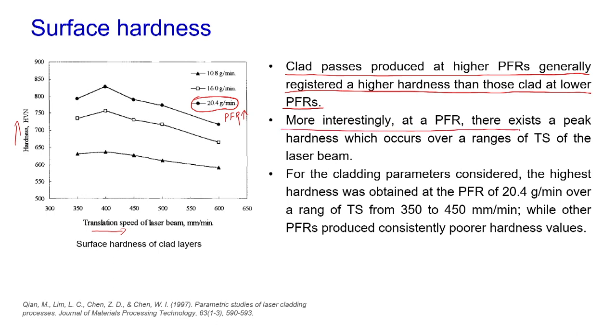Interestingly, at a PFR, there exists a peak in the hardness which occurs over a range of the TS of the laser beam. If you just notice over here, a peak occurs in the hardness and then it is reduced. The hardness increases, attains its peak and then comes down. This is achieved at a range of about 350 to 450 mm per minute for the TS, the translation speed, and for the higher value of PFR, that is about 20.4. So for 20.4 and between 350 to 400, the maximum hardness was achieved.